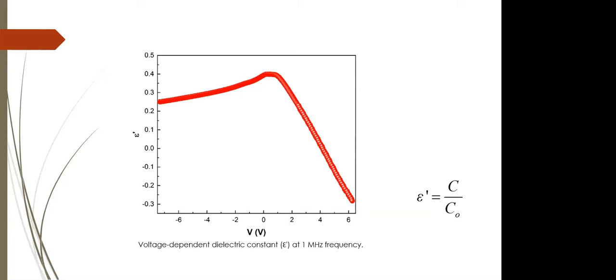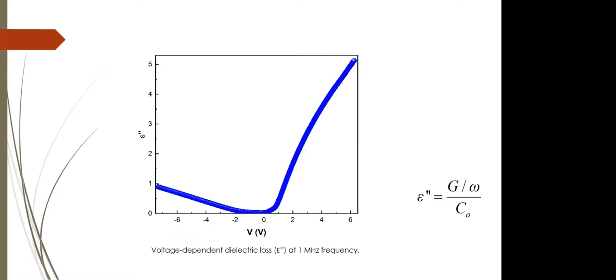This inconsistent behavior in the depletion and accumulation region of the dielectric constant is due to the interfacial states localized at the metal semiconductor interface, surface, and dipole polarization and the series resistance effect. Now we will talk about the dielectric loss parameter.